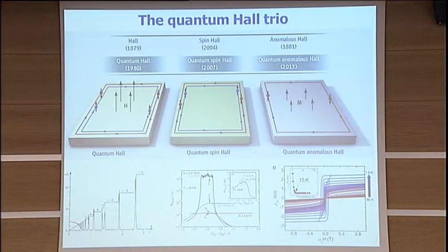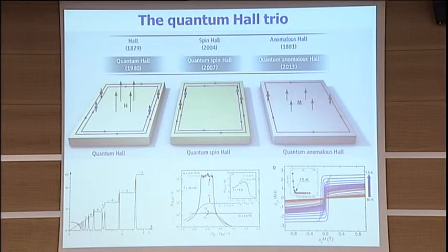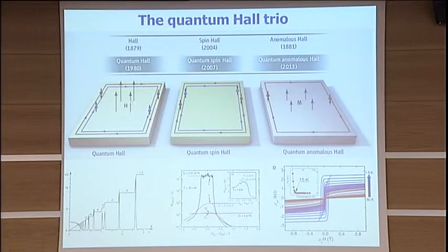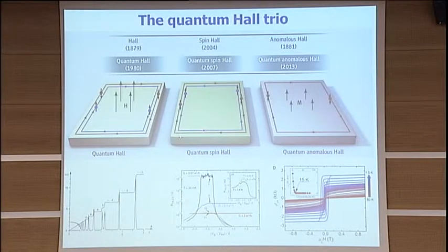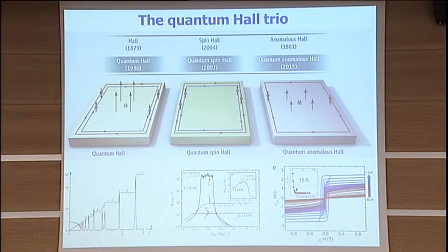In this case, you have a system with time reversal symmetry but a strongly spin-orbit coupled system. It's not surprising that the first realization of the 2D topological insulator — the Quantum Spin Hall Effect — occurs in mercury telluride, mercury being a heavy element with very strong spin-orbit coupling. The system is insulating in the bulk, but there are edge states. In the Quantum Spin Hall Effect, the edge states are counter-propagating and related to spin — spin-up going counterclockwise and spin-down going clockwise. This was experimentally observed one year after the theoretical prediction by Laurens Molenkamp's group.